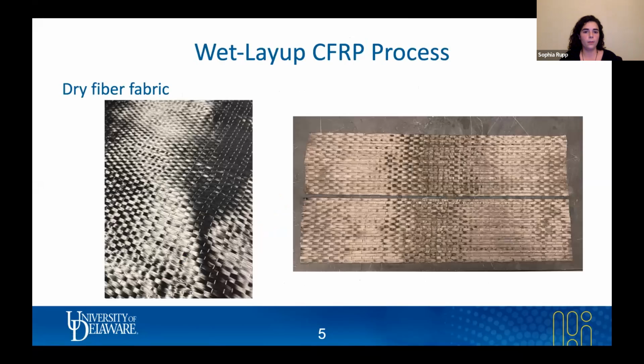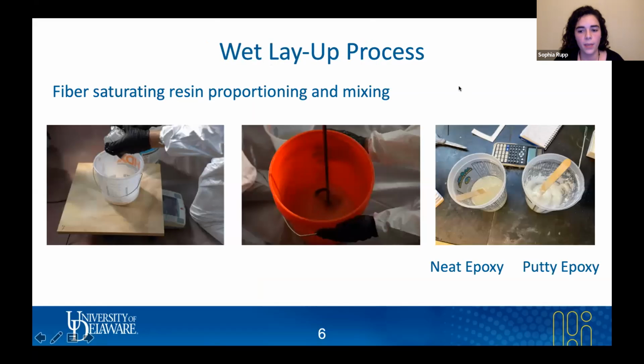There are a few different methods that can be used to fabricate CFRP. The method that I'm specifically using in my research is known as wet layup, or to put it in simpler terms, it's just fabricating the CFRP using your hands. And the way you start this process to apply it and to strengthen a concrete member is to first cut your dry fibers out, depending on how much you need. And then you can mix your neat epoxy and your putty epoxy. Neat epoxy consists of two components. It consists of a part A and a part B that need to be proportioned and then mixed together. And then putty epoxy, or what is also known as thickened epoxy, consists of the neat epoxy mixed with silica fume.